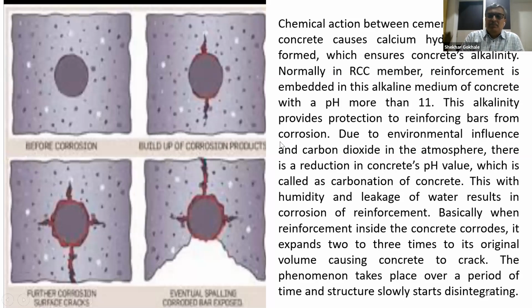So basically, this is the major cause of our problem, because in olden days we used a nominal mix of M15 grade, where the durability aspect was never considered. Only the strength aspect was considered, and the IS 456 code of 1964 or 1978 allows a minimum grade of concrete as low as M15. So durability was not considered at that time, and this is the basic cause of all these structural defects due to corrosion. If the grade of concrete had been higher in olden days, this problem could have come a little later.